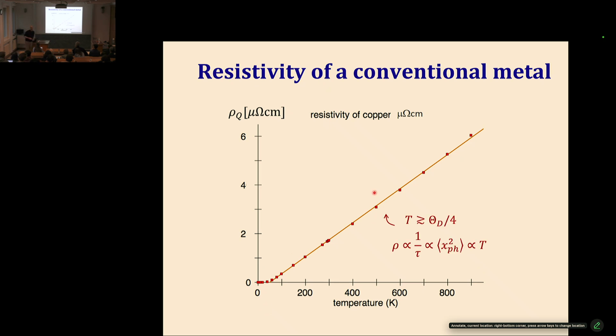So what's going on here is that the electrical current is carried by these quasi-particles. The mechanism that limits the resistivity is scattering of the quasi-particles off phonons, which are basically vibrations of the crystal lattice. At high temperature, this scattering rate of quasi-particles off phonons is linear in temperature. At low temperature, which is below some fraction of the characteristic energy of the phonons, that crosses over to T to the fifth power. At very low temperature, the dominant scattering mechanism is expected to be electron-electron scattering.